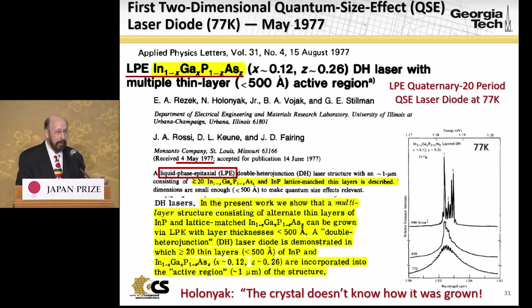Bell Labs was growing thin gallium arsenide layers, and the students at Illinois were growing thin quaternary layers, an entirely more difficult prospect, and again by LPE, but showed quantum size effect in their lasers, only pulsed at low temperature, 77 Kelvin. So these didn't operate at room temperature. They had 20-period quaternary quantum size effect laser diodes.